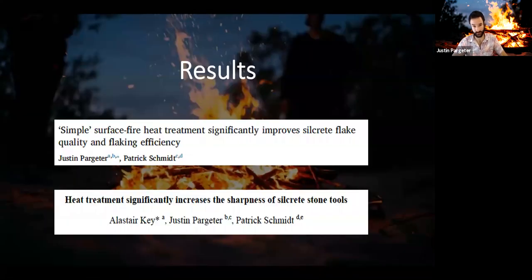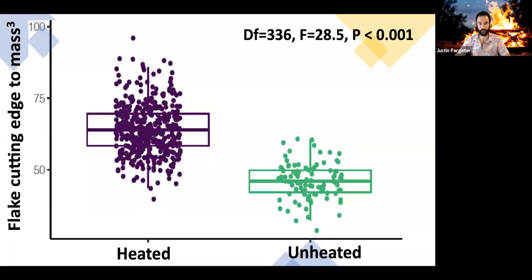Now for the study results. The results you're about to see are hot off the press in 2 papers published with the Journal of Archaeological Science Reports, and a second upcoming in the journal Archaeometry. Our first results showed that surface fire heated silcrete produced a significantly higher amount of flake cutting edge to mass on flakes compared to unheated silcrete.